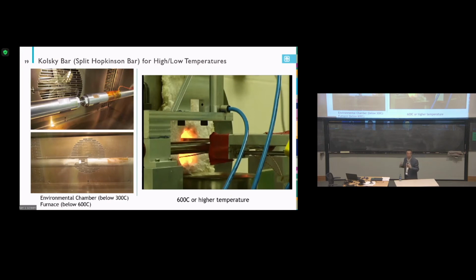And another example is how to simulate a forging process. In the forging process, you heat a big chunk of material to a very high temperature, put it there, use the die, use the pound, basically just make some metal forming. After that, you put it back into water or oil for quenching. How can we understand this whole process? How does the material microstructure change during this whole long process? How can we simulate this process? So that's why we developed what we call the robot Hopkinson bar. Because we cannot heat the Hopkinson bar to a high temperature, we have to heat the specimen individually, separately.